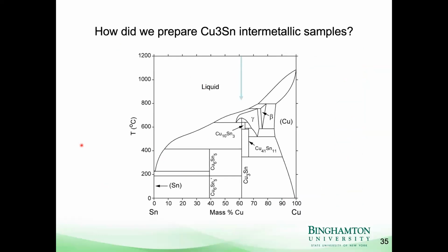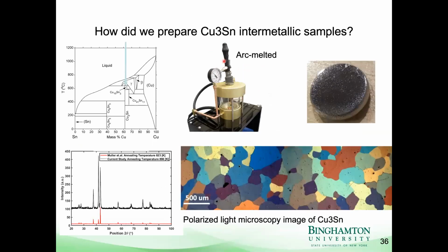So how do we prepare Cu3Sn? You may think it's pretty easy. We just mix 3 parts copper and 1 part tin, melt it, and then cool it down. But there's a little bit of a trick that's required. If you melt it and cool it down just in a furnace, you'll pass through this gamma phase, and you won't end up with pure Cu3Sn. The way around this, we got help from Professor Eric Kotz in physics, and we used an arc melter. I'll have a picture on the next slide. It's basically a welding torch in an inert environment, and you put your metal on this copper liquid cooled hearth. So it allows you to melt and cool the sample really rapidly.